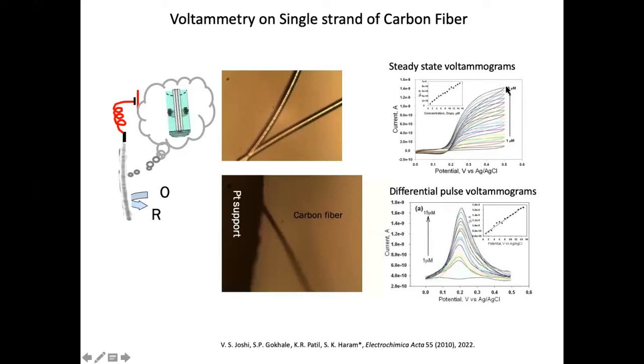Basically, in this case, a steady state voltammogram is measured as a function of dopamine concentration from 1 micromolar to 15 micromolar. Here you have plotted the steady state current versus concentration, and it changes linearly. Here in this case, differential pulse voltammetry, I'm not going to discuss, but I want to illustrate at this point that carbon fiber is basically an excellent electrode material for dopamine sensing.